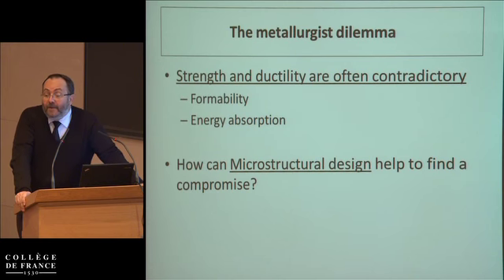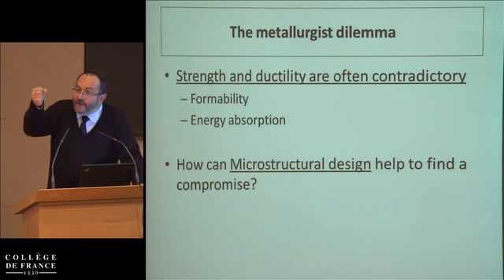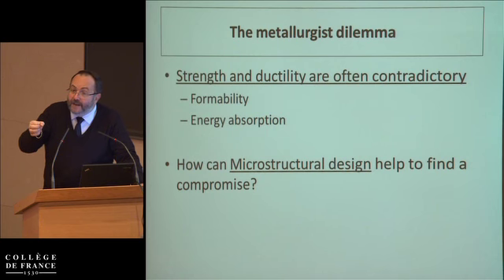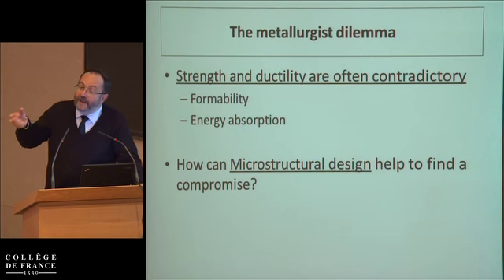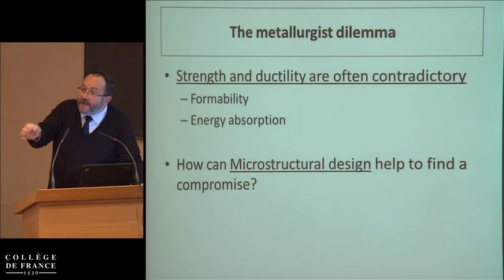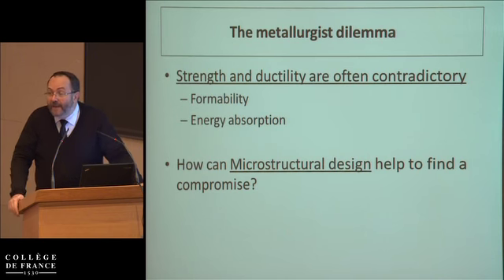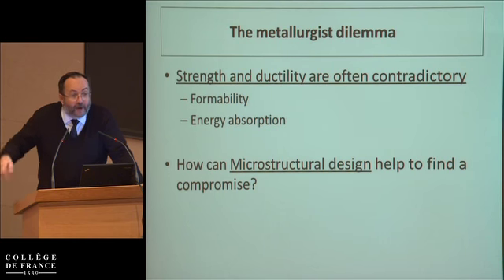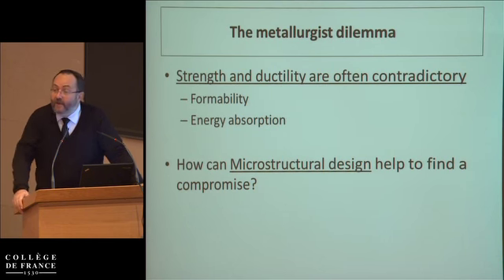Now, if you look at the possible localization of deformation, if in some region of the sample that you are putting in tension, the deformation gets more localized, at this point you have a higher yield stress, of course, but you have also a lower section. If the increase in flow stress, which is basically related to the work hardening, cannot match the increase in local stress, which is a reduction in section, then you will get into trouble. And getting into trouble means the localization of deformation will go on forever and will lead to a rapid failure.